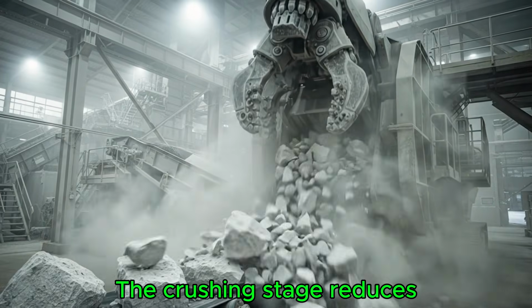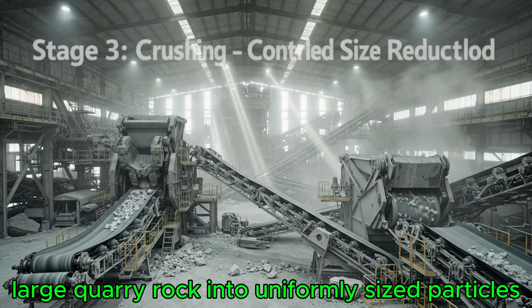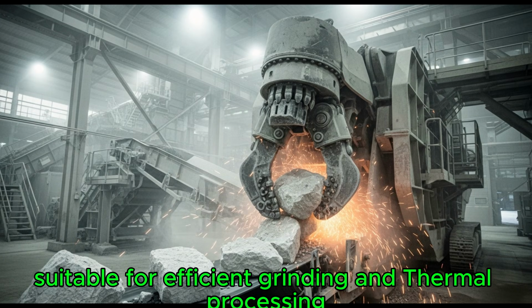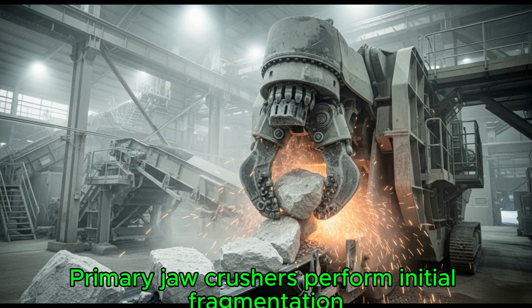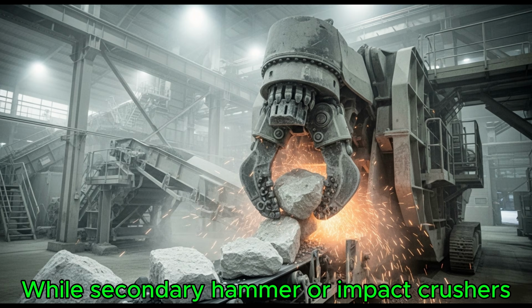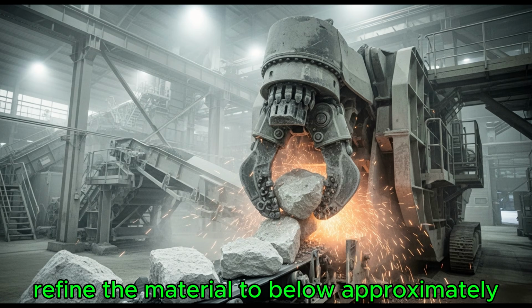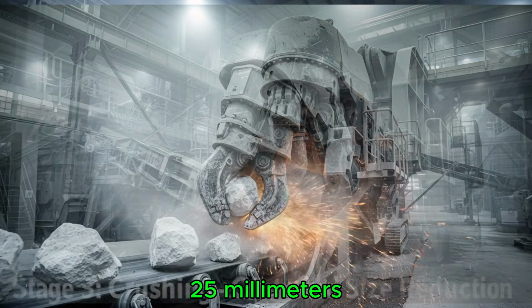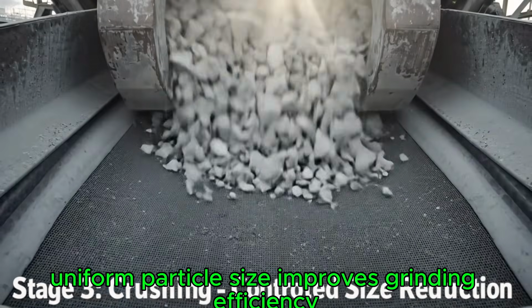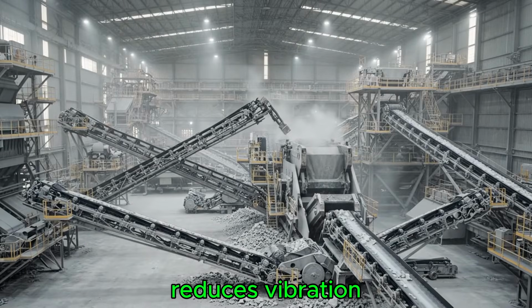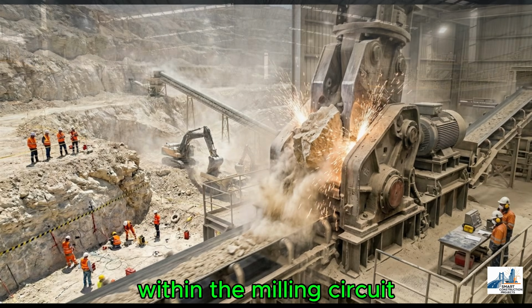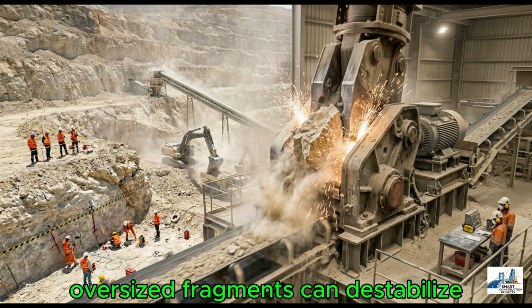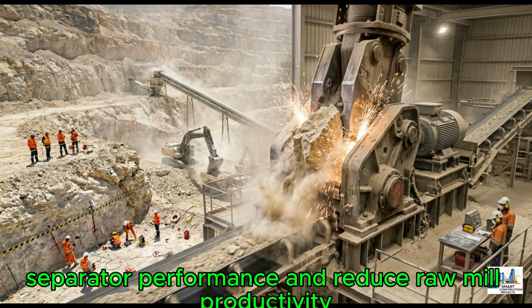The crushing stage reduces large quarry rock into uniformly sized particles suitable for efficient grinding and thermal processing. Primary jaw crushers perform initial fragmentation, while secondary hammer or impact crushers refine the material to below approximately 25 millimeters. Uniform particle size improves grinding efficiency, reduces vibration, and lowers electrical power consumption within the milling circuit. Oversized fragments can destabilize separator performance and reduce raw mill productivity.